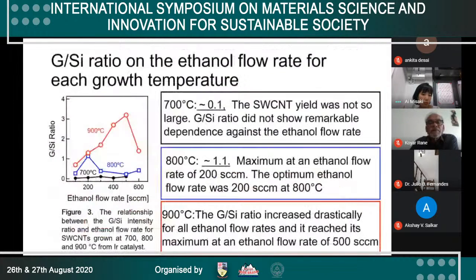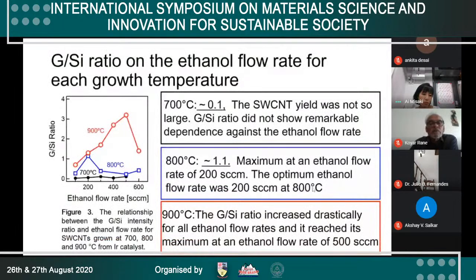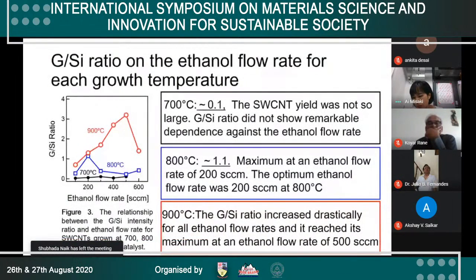Moving on to the next slide, figure 3 shows the relationship between the G/Si intensity ratio in Raman spectra and ethanol flow rate for SWCNTs grown at 700, 800, and 900 degrees C from iridium catalyst. When the growth temperature was 700 degrees C, the G/Si ratio was kept under 0.1. At 800 degrees C, the G/Si ratio increased. It reached its maximum at an ethanol flow rate of 200 SCCM, where the G/Si ratio was about 1.1.